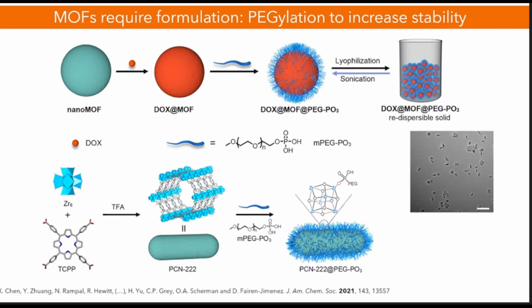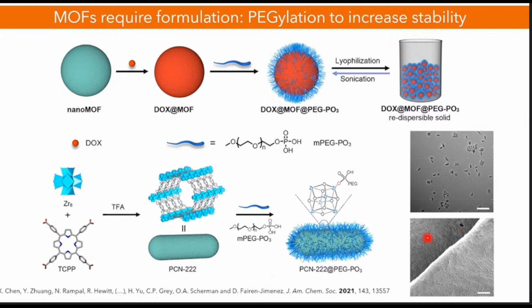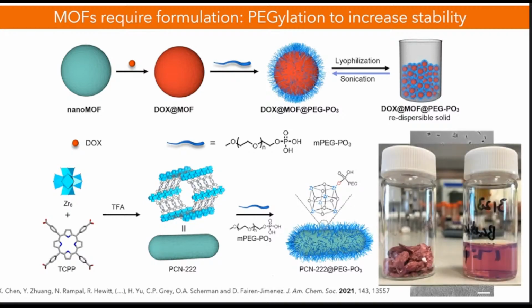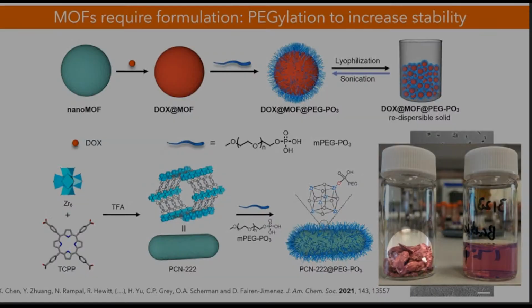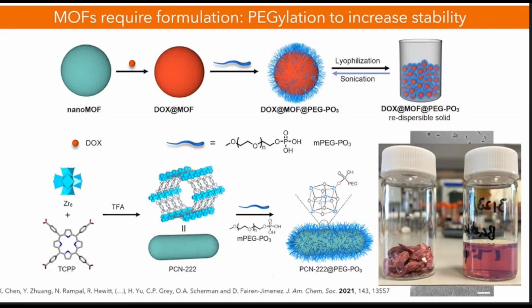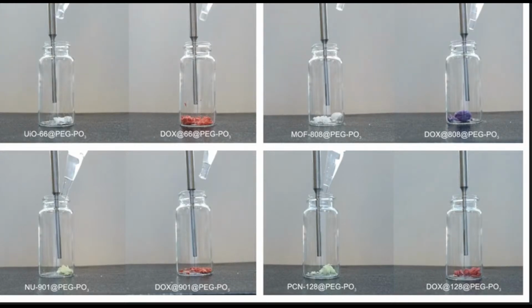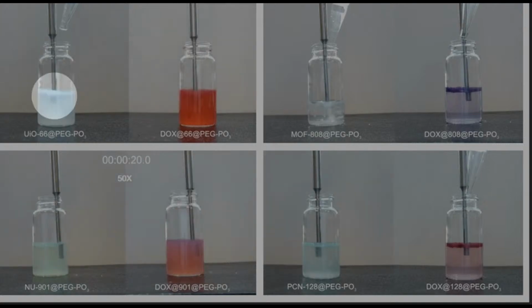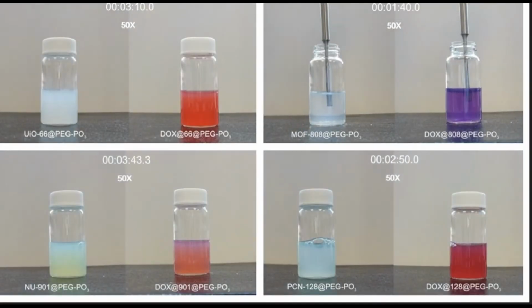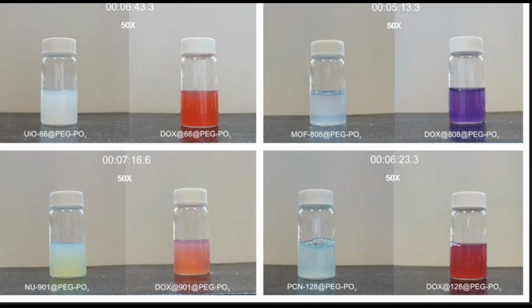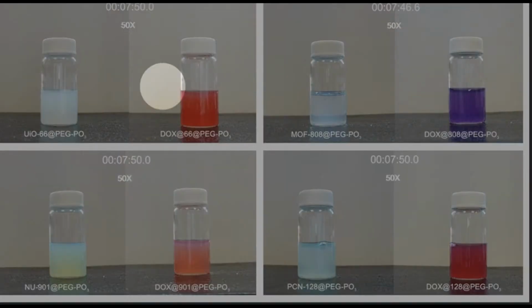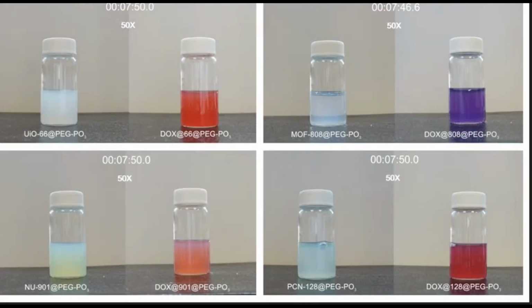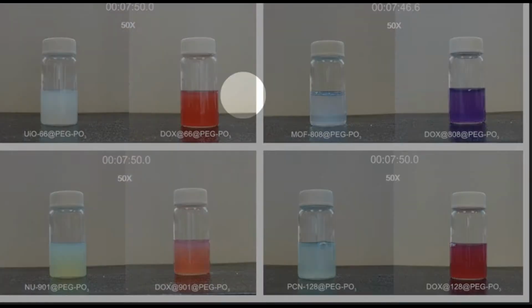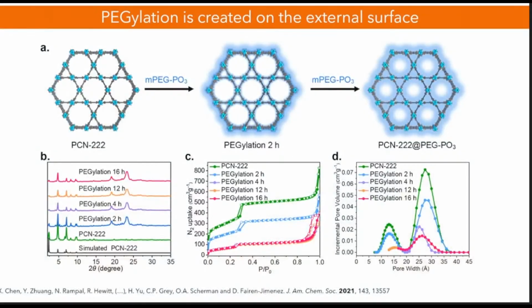This is how the materials look under the microscope. Beautiful 100 nanometer nanoparticles, some rod shape. And this is how the material looks when it's dried, and you can see everything is very well defined, all these individual particles, and everything is very well connected with these pegylation groups. This is the material in solution, and this is the material when it has been dried under this lyophilization process. This is very important, because as I said, we can really redisperse all these materials. This is the empty material, this is loaded with doxorubicin, hence the color. And you can see here in the video, we include some sonication, we include the solvent, and we can really have something that is going to be colloidally stable for a few days. We have been doing this for several days, and we don't see any drop, any precipitation of the materials. So very happy with all these different possibilities when including the pegylation into the materials.